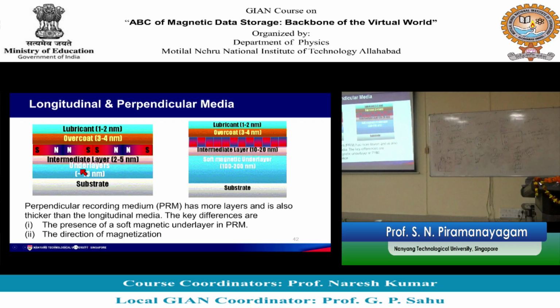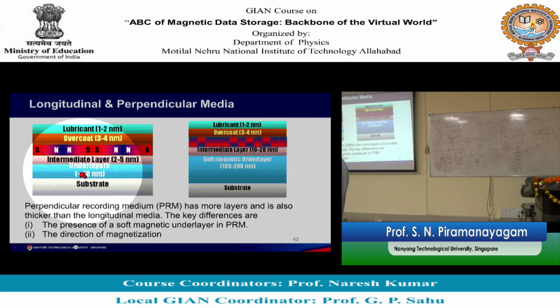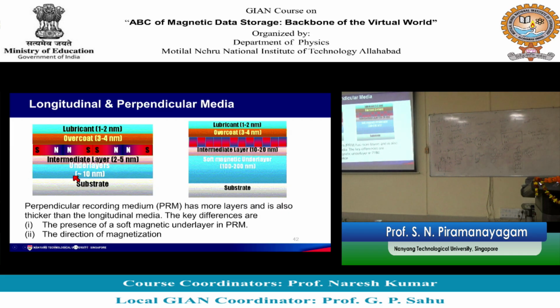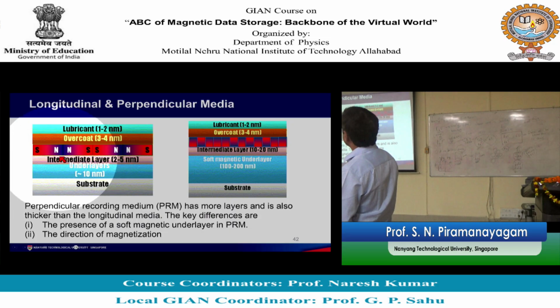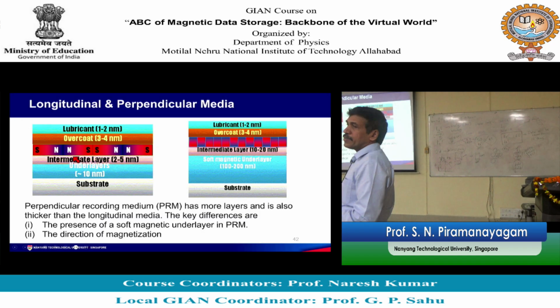You remember I showed you one picture of chromium below the cobalt. So that chromium will grow with a certain texture, and when you grow the cobalt on top of that chromium, then you will have the C axis parallel to the disk surface. Okay. So we grow these layers to make the magnetization easy axis to be parallel to the substrate.